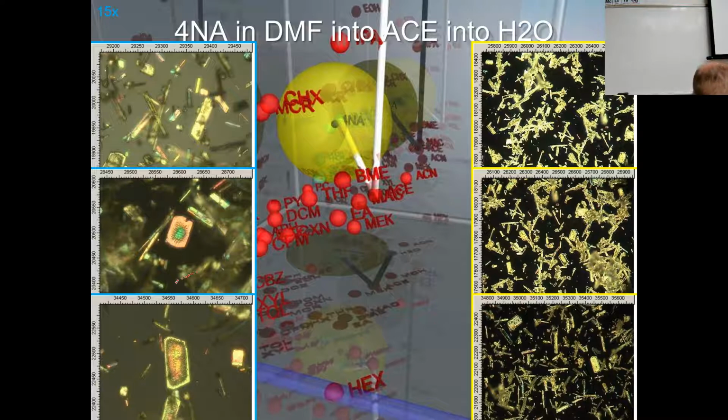And so here's a nice plate. And now what's this funny business in the middle? So it's a plate, and if you really zoom in on it, it looks a little dirty in the middle here. And this one too, it's got some mottled area too. That's solvent that was stuck to that surface and then finally came off. And so you've got pits.